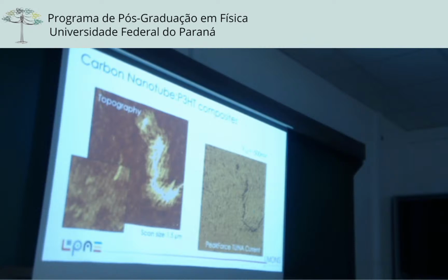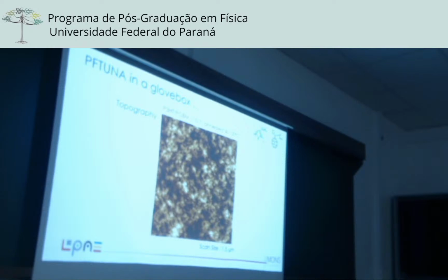We can spend days because the tip is gently landing on the surface, making the measurement, and then going to the next pixel. There is no wear of the tip on the sample, which means that you can keep the coating on your tip. Another example, P3HT PCBM. Here, this is topography. And most of the time in the literature, 20 years ago, people said, okay, we can clearly see the P3HT and the PCBM. I have 30 years of experience in chemical microscopy. This is a privilege of age.